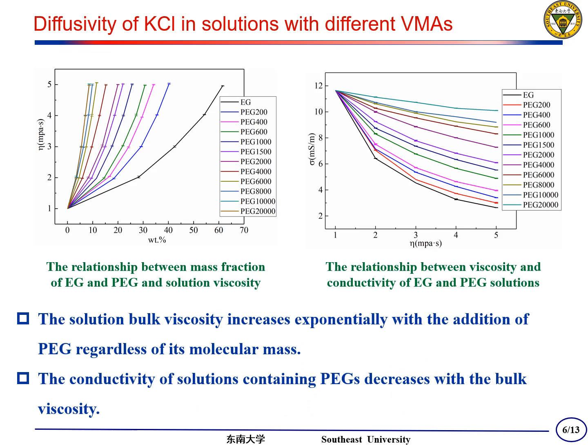The solution bulk viscosity is often assessed through the values of solution conductivity, so we use the polyethylene glycol, also called PEG, with different molecular mass as the VMA to characterize the diffusion behavior of chloride on the different given bulk viscosity by conductivity test, showing that the bulk viscosity of solution increases exponentially with the addition of PEG regardless of its molecular mass, and the conductivity of solution containing PEGs decreases with the bulk viscosity.